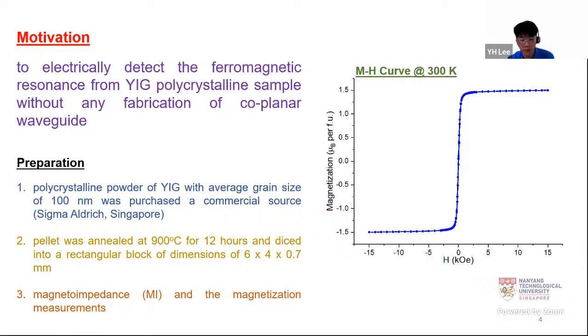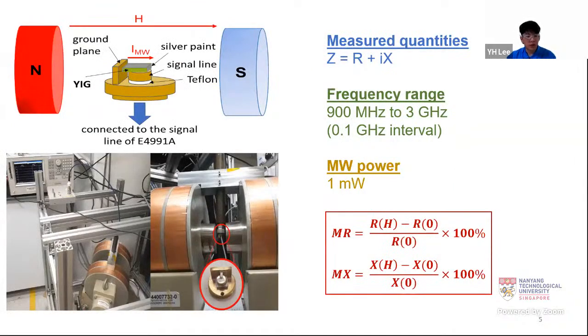the magnetic impedance measurement. How do we do the connections? Allow me to share, so we start from the bottom left. The one I circled using my mouse, we can see that there's this machine, the E4991A single port impedance analyzer. That is where we do our measurements. So the sample, the similar rectangular block that I did for VSM measurements, is now mounted onto the sample probe on the top left using the silver paint. So I paint both sides, both ends and at the top.